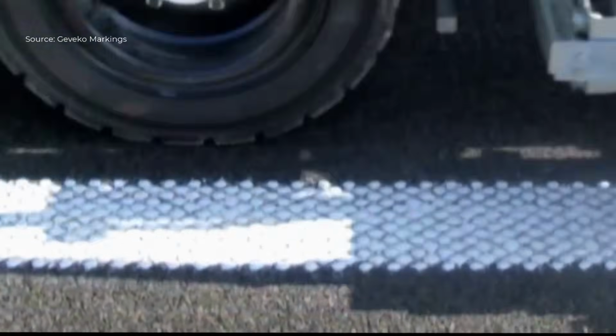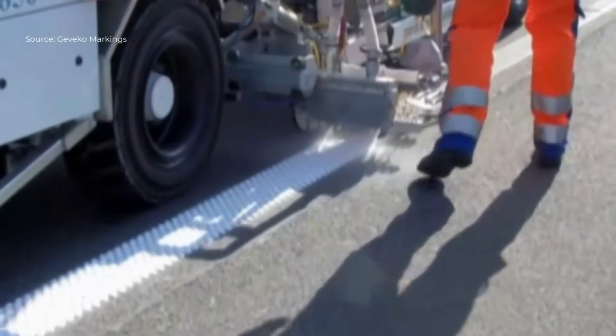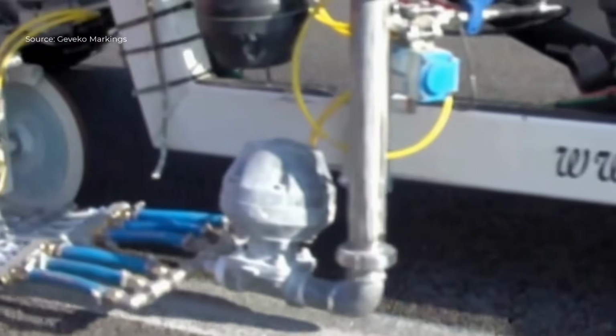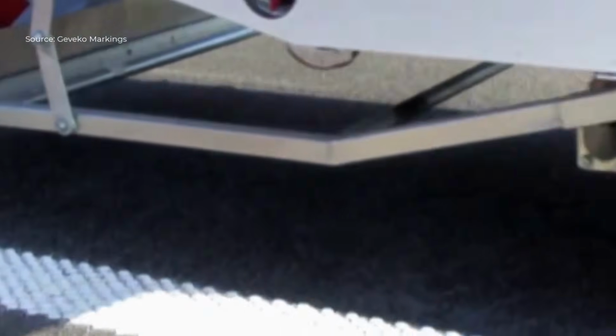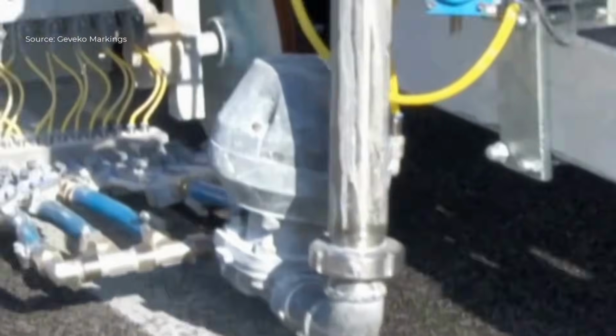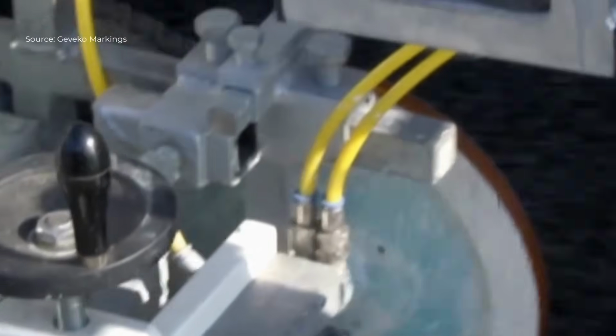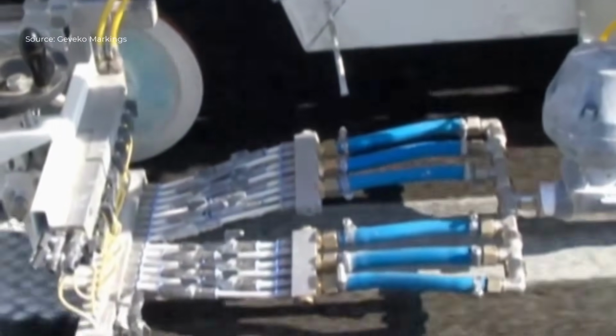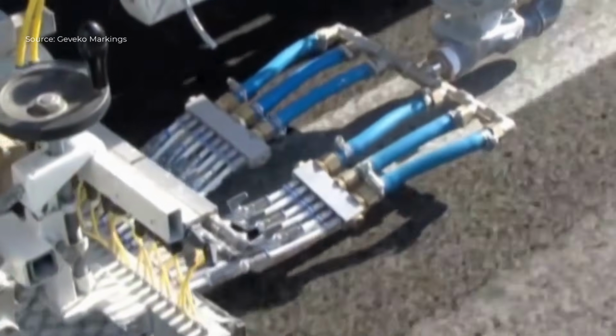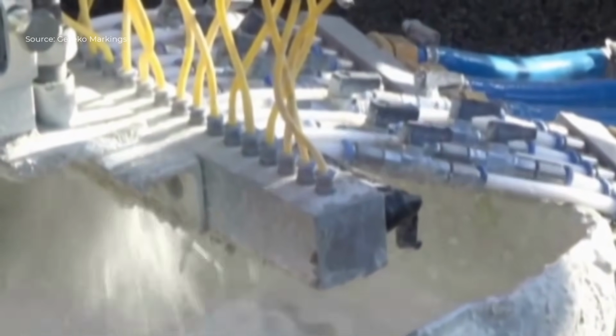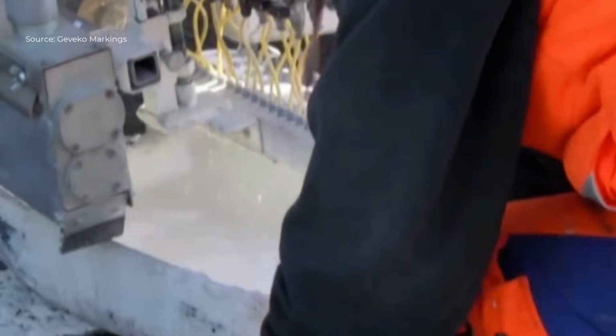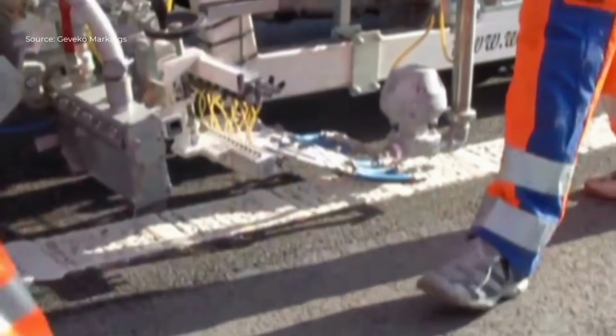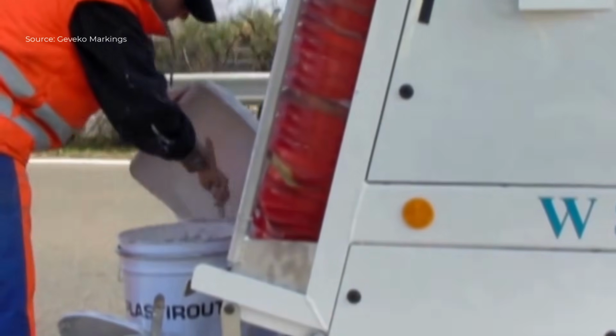Designed for highways and other heavily trafficked areas, Spotline delivers strong retro-reflection, especially at night, and under wet conditions. The PlastiRoute Spotline material is a paste-like, solvent-free cold plastic that cures through a peroxide initiator, ensuring long-lasting performance. During application, the marking machine lays down the cold plastic in an agglomerate pattern while simultaneously distributing fine drop-on beads. This advanced Spotline technique produces a textured Type 2 marking that enhances visibility, skid resistance, and overall driving safety.